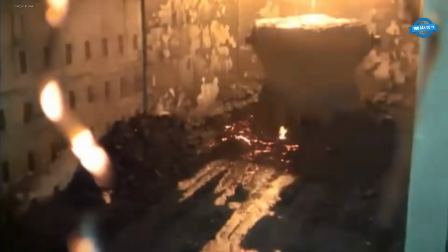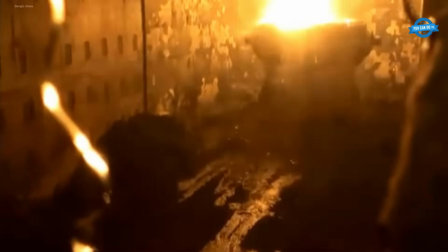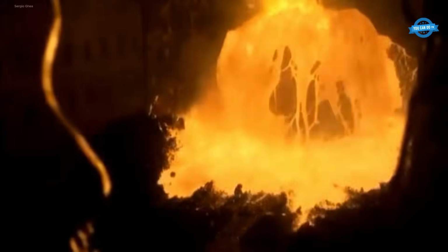The cause? Likely moisture or trapped water hidden beneath the slag, instantly vaporizing into high-pressure steam the moment it contacts the molten steel. The furnace convulses, fire and gas erupt outward, and molten metal sprays with terrifying force. It's a brutal reminder of the raw, untamed energy inside every EAF. Even the smallest oversight, wet scrap, residual water, can trigger a catastrophic chain reaction.